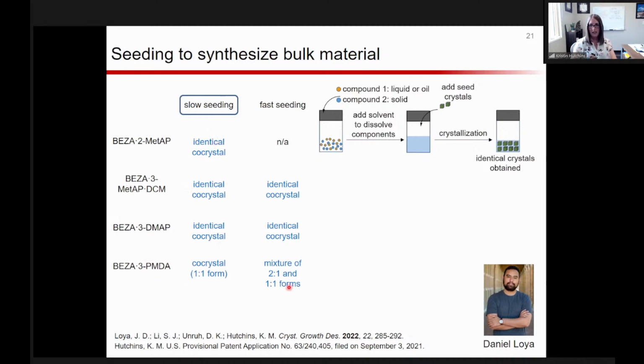And in the 3-PMDA case, which I think might be the most interesting, this was such an odd case where we almost wanted to call it a disappearing polymorph, or a disappearing form. So that was a very initial experiment we did with it. Our first milling experiment, first dissolution and solution, gave us the 2-to-1 form. And then following that, when we started doing milling and just repeating our experiments, we actually kept getting the 1-to-1 form. And we did get this 1-to-1 form by seeding. So looking at these two forms, and also looking at the structure, I think it's very likely that the 1-to-1 form is the thermodynamically stable form, and the 2-to-1 is probably a kinetic product. Again, especially looking at the structure and thinking about which type of packing or interactions would be favorable.